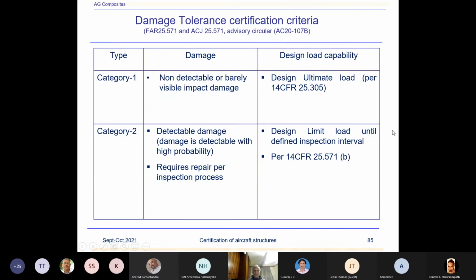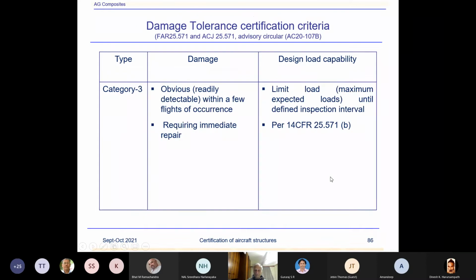Right. Okay, now category 1 damage, non-detectable or barely visible impact damages. This is designed to design ultimate load. Category 2, detectable damage. Damage is detectable with a high probability during walk-around. Requires repair per inspection process when they are detected. That is after 2 inspection intervals. Because you don't repair every time the damage is found, you will just ignore it if the residual strength capability is higher than limit. Design limit load until the defined inspection interval. That is 2 inspection intervals normally we define.